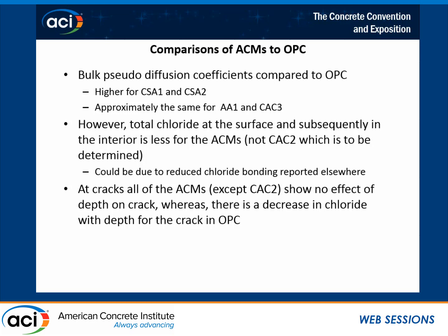However, the total chloride at the surface and subsequently in the interior is less for the ACMs, which is yet to be determined. At cracks, all the ACMs, except the CAC2, which I didn't show, show no decrease in chloride with depth of crack, whereas there's a decrease in chloride with depth for an OPC.